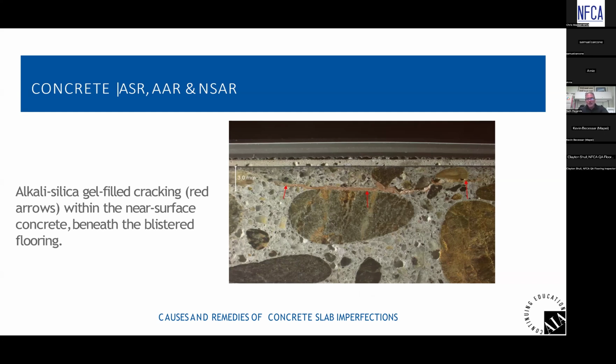Just a picture here. I mean, you saw the previous picture, but this is petrographic analysis of concrete and a third-party lab that confirmed that the material above the red arrows is a gel-filled cracking, alkali silica reaction gel that filled the crack once the reaction and the crack happened.